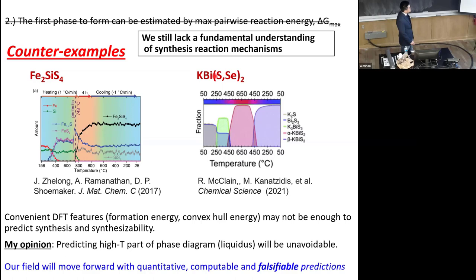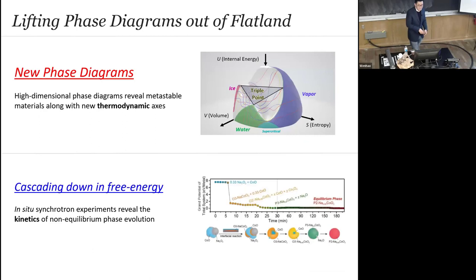My perspective is that DFT features that we can calculate today, formation energy, convex hull energy, may not be enough to predict synthesis and synthesizability. If we want to understand solid state synthesis, we cannot avoid trying to model the liquid free energy. And if we do this, then I think we can start to move towards predictive synthesis, okay? So that's basically my talk today. I'm trying to explain to you some ideas of lifting phase diagrams out of Flatland.